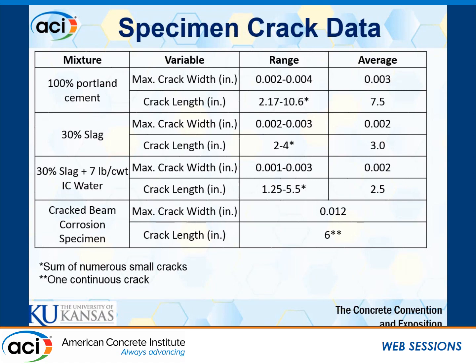So we'll start with the top. With our 100% Portland cement mixes for settlement cracking, we have a range of 2 to 4 mil wide cracks, average around 3 mils. Crack lengths between 2.17 and around 10.5 inches, average length of 7.5 inches over a total of 12 inches of that bar.